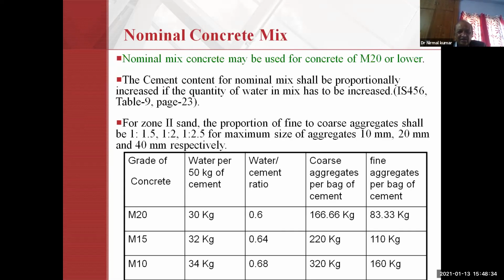नॉमिनल कंक्रीट मिक्स का एक टेबल कोड आईएस कोड में दिया हुआ है. Concrete less than M20 grade. In Table number 9, page 23, you can see it in the IS code, which I have reproduced here for M20, M15 and M10 grade, in which per bag of cement the water requirement is 30 kg, 32 kg and 34 kg respectively. And the water cement ratio will be limited to 0.6, 0.64 and 0.68. And coarse aggregate weight is also given, and fine aggregates. But beyond M20 grade of concrete, you should go for the mix design.